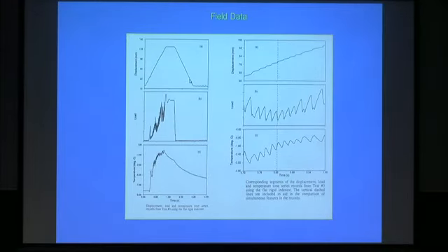Actually, for the ice island, I had put a thermocouple in the center of one of the pressure sensors. And we got some really interesting data from that. So this is the temperature measurement from that thermocouple. And as you can see, the ice started out at around minus 8.5 or so. And by the end of the test, it was up to 0, indicating that there was some liquid present.